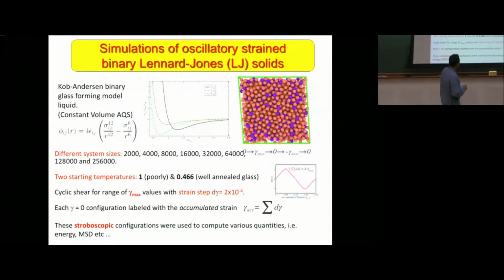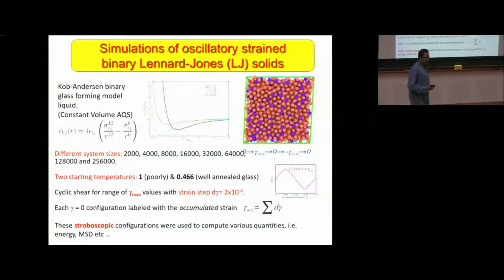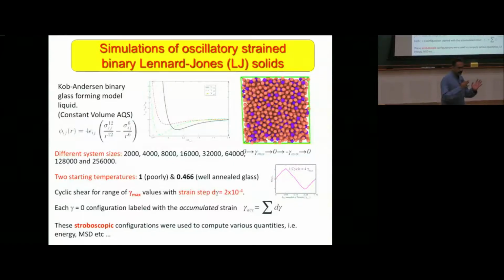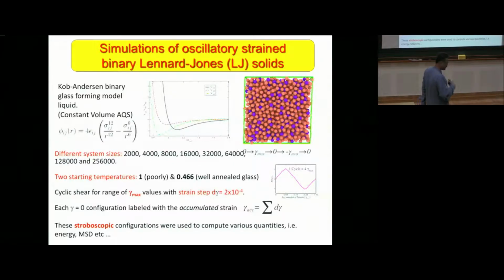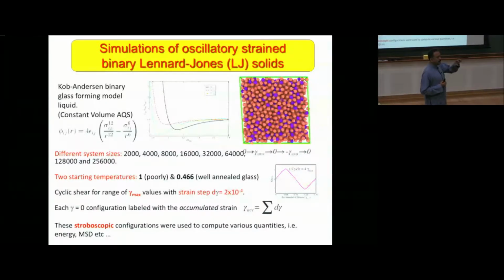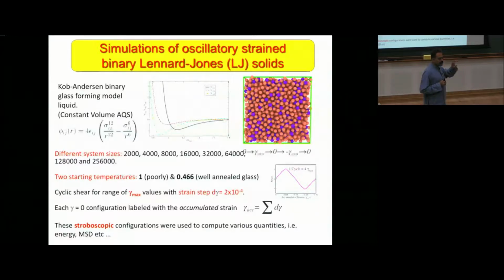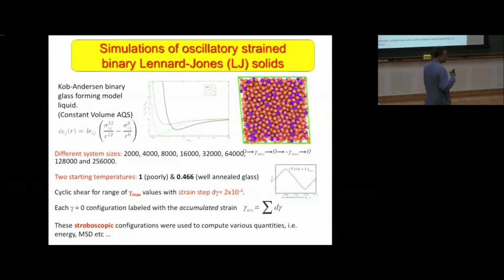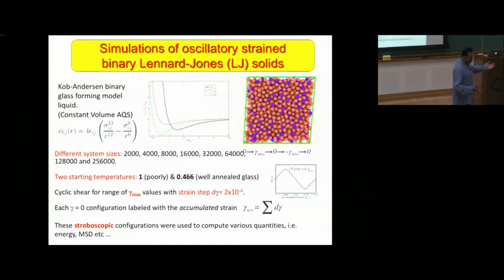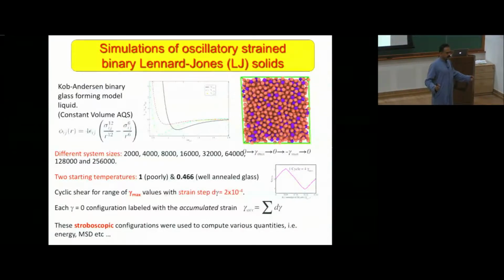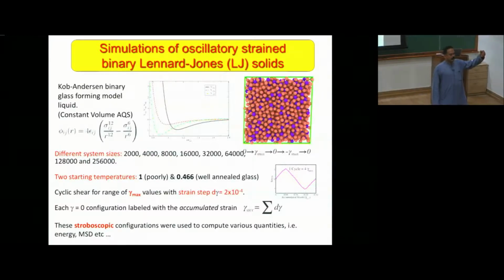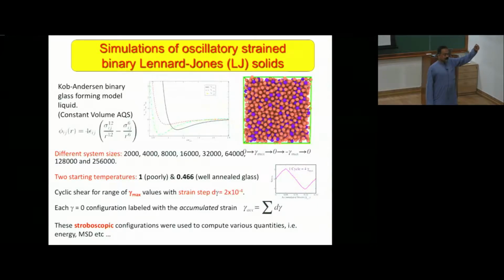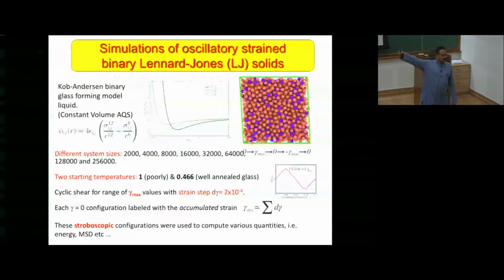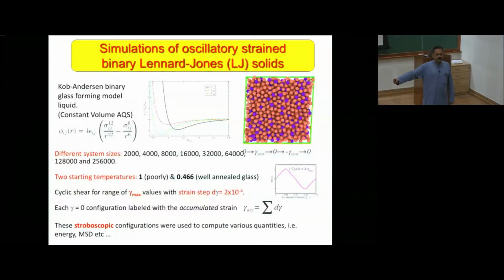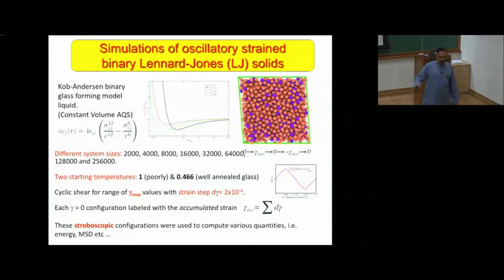And so there is one control parameter here, which is the amplitude of the deformation, and that's the only control parameter. But there is a second important parameter, which is how annealed the glass is that you start with, right? To understand the effect of that, we basically work with two glass samples, which we treat as our initial configurations. One is an energy minimum structure that is obtained by quenching a high temperature liquid, and the other is what we obtain by quenching a low temperature liquid. These we refer to as poorly annealed and well annealed.